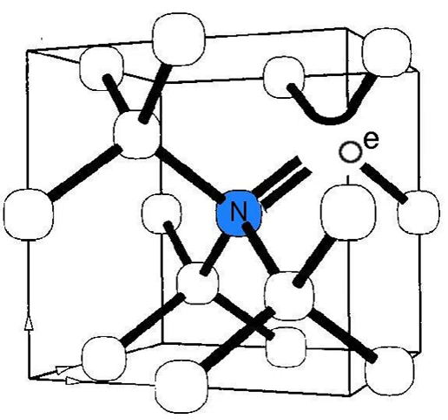One can visualize this by imagining the 3 unpaired vacancy electrons continuously exchanging their roles. The NV0 thus has 1 unpaired electron and is paramagnetic. However, despite extensive efforts, electron paramagnetic resonance signals from NV0 avoided detection for decades until 2008. Optical excitation is required to bring the NV0 defect into the EPR detectable excited state. The signals from the ground state are presumably too broad for EPR detection.